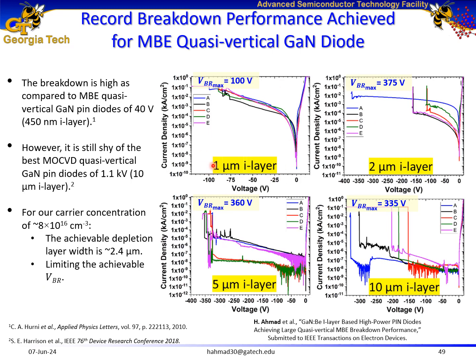In this slide, I have shown the JV characteristics of my pin diodes for I layer thicknesses of 1 micron, 2 microns, 5 microns, and 10 microns. And I've shown the maximum breakdown performances of each individual kind of device as well. And the maximum breakdown voltage of 375 volts is a record breakdown voltage for gallium nitride based pin diodes grown via molecular beam epitaxy.